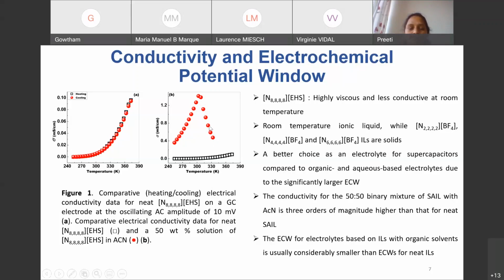These red solid circles are the binary mixture of tetraoctyl ammonium ethyl hexyl sulfate, and the black squares are for the neat ionic liquid. And we can see a large increase in the conductivity. But there is a limitation. We cannot use this binary mixture beyond 300, because then the conductivity starts reducing. There might be two factors. First, acetonitrile is volatile, and another is that maybe some aggregates are forming, which we haven't focused on because we were not interested in that.